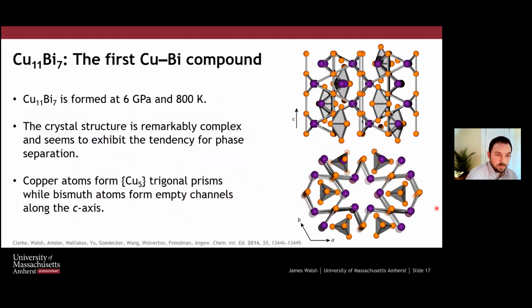And in this system, we found the first copper bismuth compound, which I'm showing here. And what I hope that you'll see immediately is that this is a pretty complex structure. It's remarkably complex, in fact. You know, sometimes we think that as you go to higher pressure, you get something more simple. So I think that was the belief for a long time. We're starting to see more and more examples where that's not the case, that high pressure may not actually just be the close-packed structure types. And so in this case, we see some phases remarkably complex.